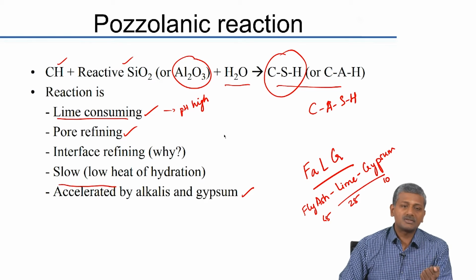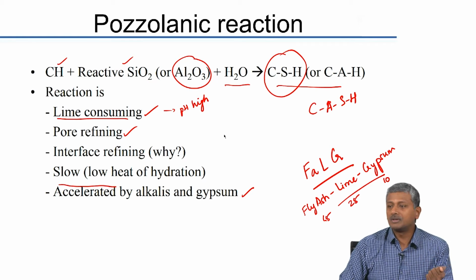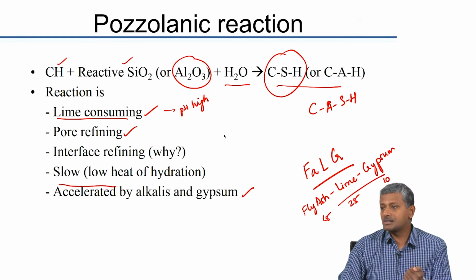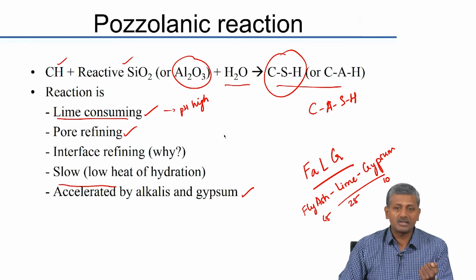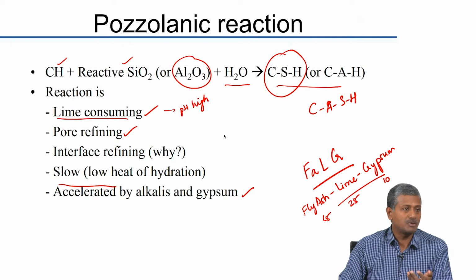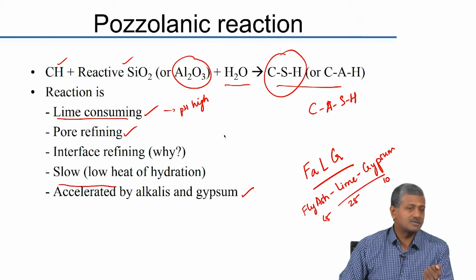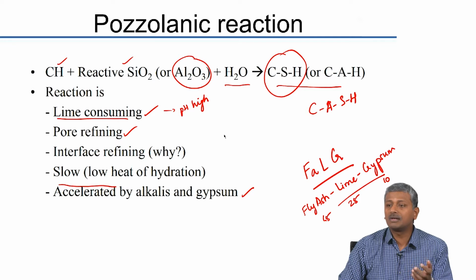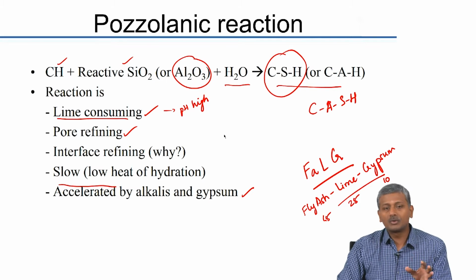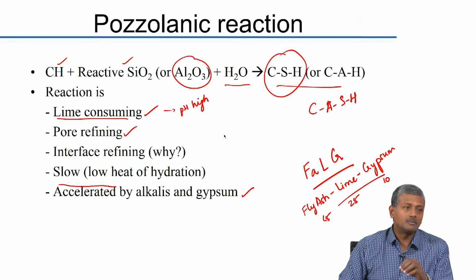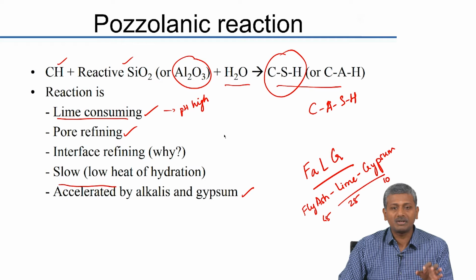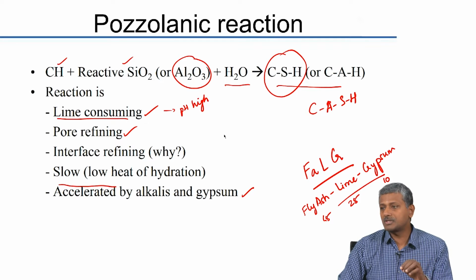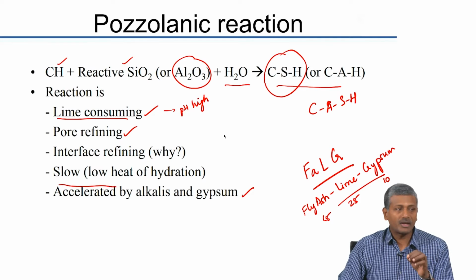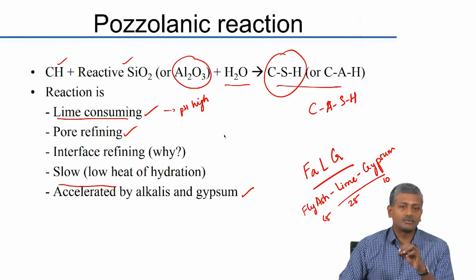So, especially when there is a chance of very low temperatures in the environment, you would not like to use pozzolanic materials like fly ash, because fly ash, however reactive it may be, its reactivity is always going to be lesser than cement. So, if you have to cast concrete at freezing temperatures, then you would tend to use normal Portland cement, unless of course you are doing heat treatment for the concrete. If you are subjecting your concrete to heat curing, then fly ash is an alternative that you can think of.